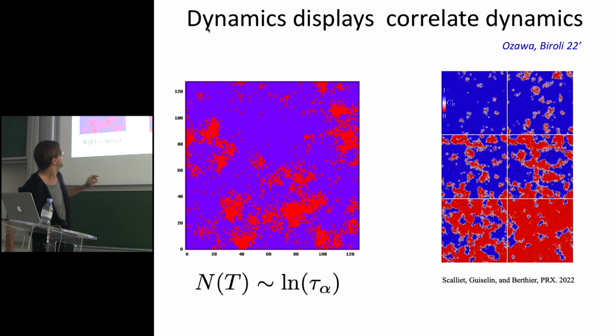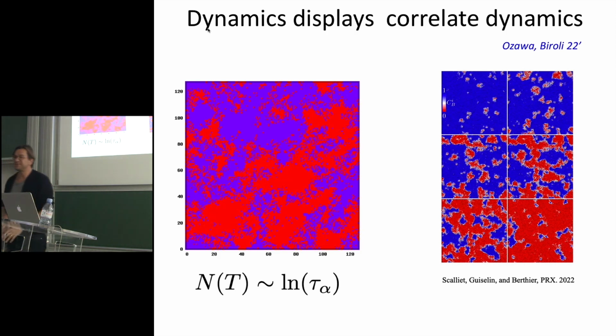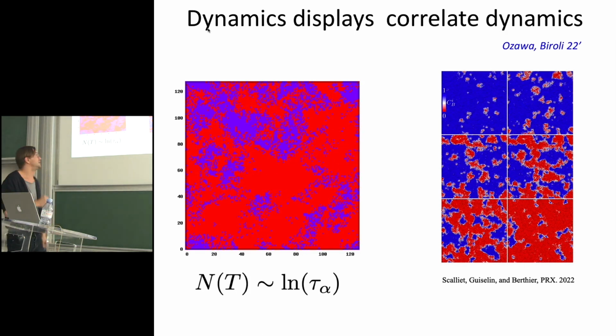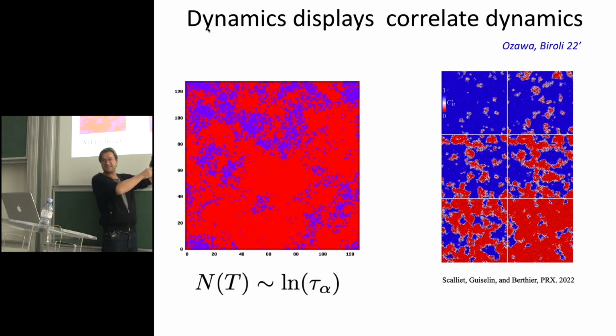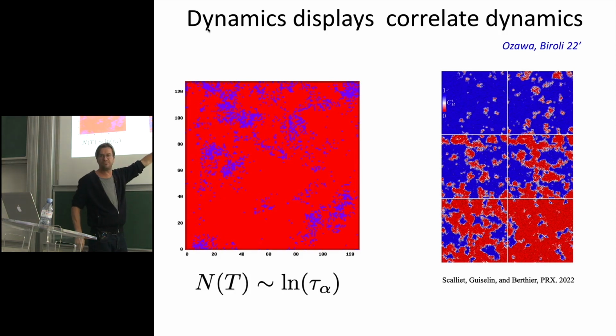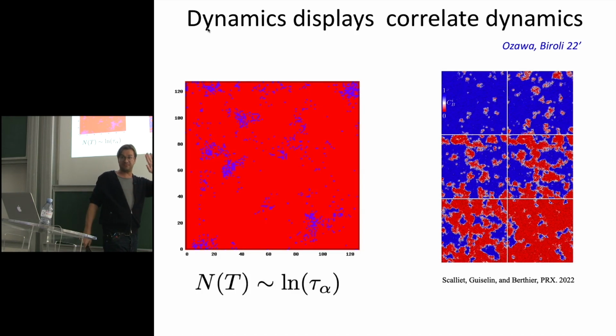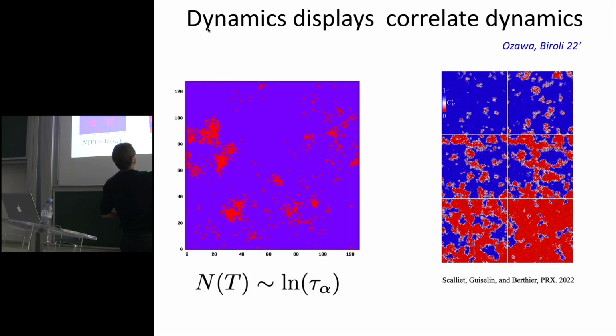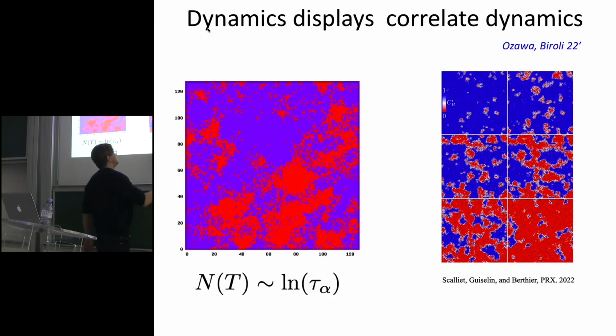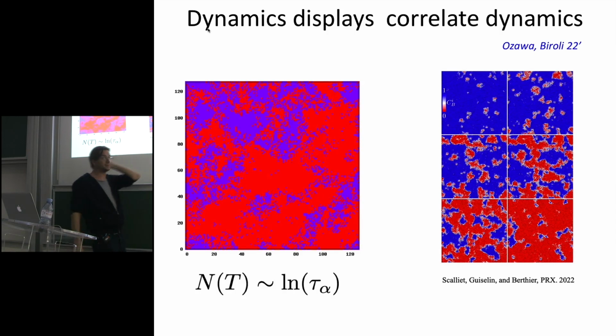And now that's where, oh, the movie? Oh yes, the movie is there, okay. The key point is that in those models, you do capture interesting collective dynamics. Here's how people visualize it in a numerical glass. You can also do it with imaging in a real glass. Those are molecular systems where you do molecular dynamics. At T equals 0, you color everything in blue, and if one region has relaxed, you color it in red. What you see is some regions that essentially relaxed. It's a sort of coarsening process where they get bigger and bigger with time. There is a characteristic scale of those dead regions where nothing happens, and that defines the correlation length I told you about.